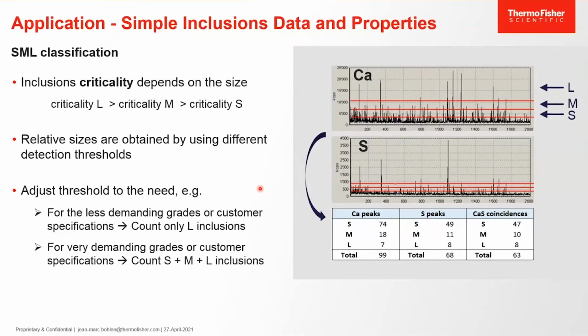So this is very interesting, knowing that criticality is not the same in all the steel grades or for all the customers. So with this kind of method, you can adjust the control parameter to the need. For example, for the less demanding steel grades or customer specification, you will count only the large inclusions. And for very demanding grades or customer specification, you will count all the inclusions, small, medium, and large.